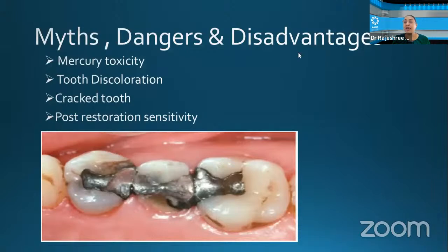So there is a place for the tooth-colored material because of aesthetics. And like you're saying, there are new materials that are reinforced with fiber, new composites that are strong, that almost replace amalgam. And what is nice is these materials bond to the tooth surface, unlike amalgams, which don't bond to the tooth surface, and you have to cut a specially designed prep for amalgams, which is not good because sometimes you have to cut a large prep just to accommodate the material.